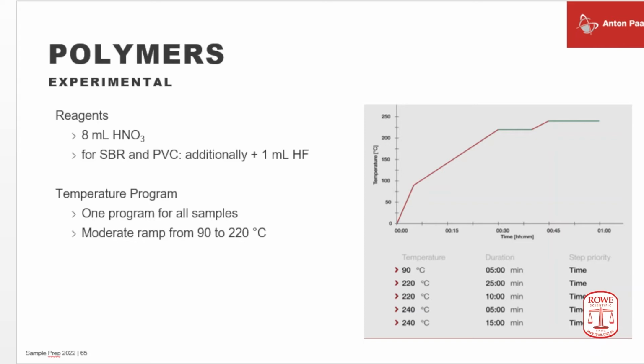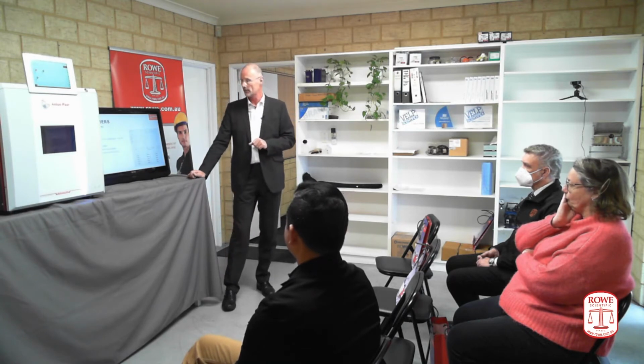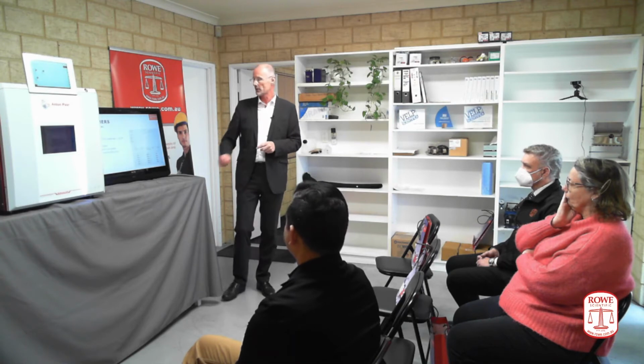So a slow heating ramp at the beginning you will see with many of our profiles. Then you leave the reaction for a while to decay until you take it up to the final desired oxidation temperature of 240 degrees in this case. Nitric acid, just nitric acid, 8 milliliters on 400 milligram material. Nitric acid does a very good job for digestion of polymers, and it is one program for all those samples.